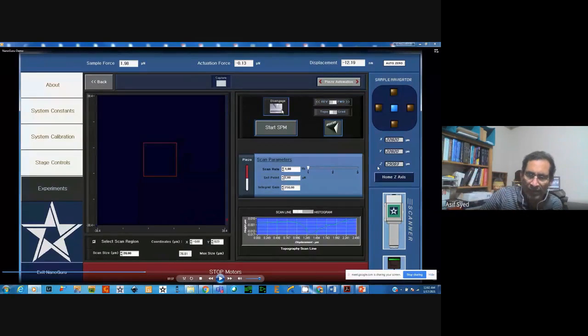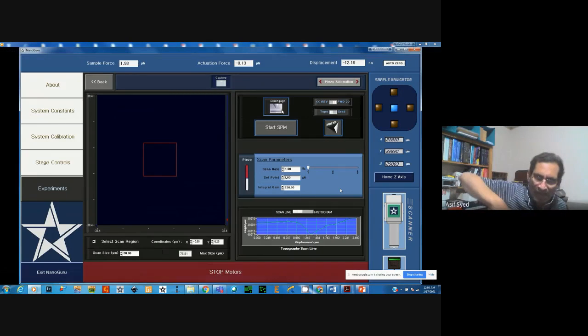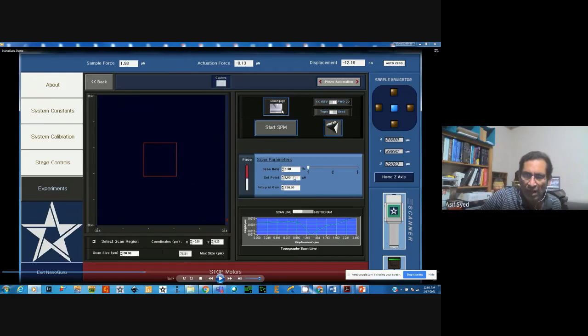What it means is that it scans one time, goes full and then comes back. So with 1 hertz, we can select, and then you say this is the force that, when you do the scanning, the force between the tip and the sample that it is going to maintain is about 2 micronewton. You put that over here as the set point, and then this is a feedback loop.